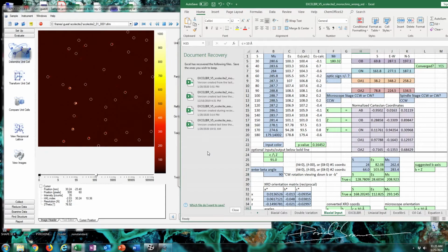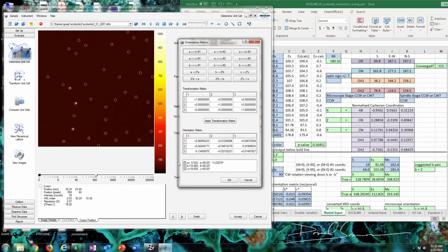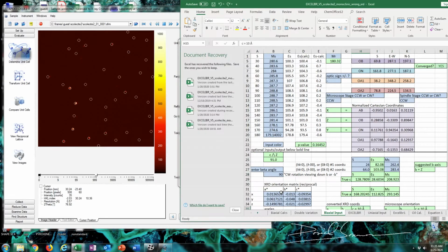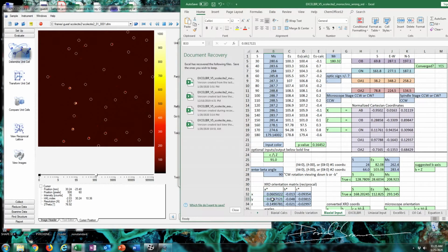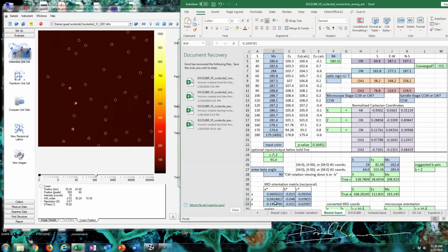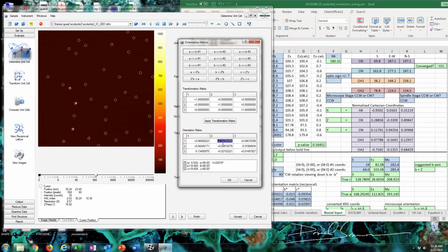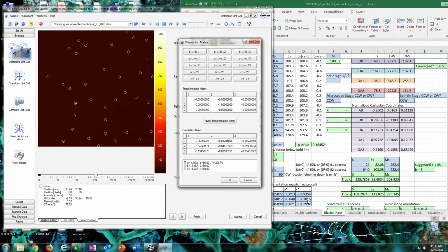And this one is really specifically unusual in that way because there are two axes that will work for the C axis in this case. So the long axis of the crystal for this is actually A. B is equal to Z in the correct setting.